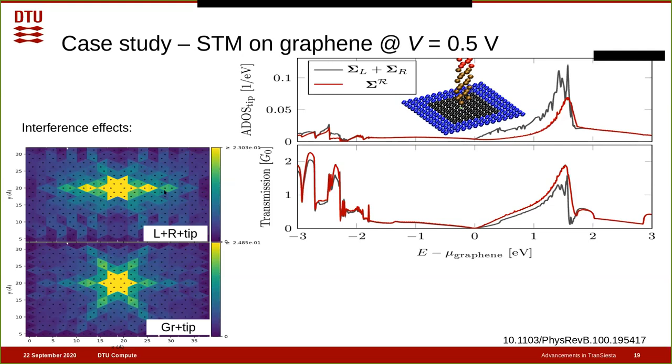Another thing is that when you plot the bond currents in this case, you can really see the effect of the interference effects. So here you have a left-right, so you have 3 electrodes, and here you have the real space self-energy. Here the neighboring tip is up on the north side of the plot, and that kills off the actual path that you will see in a correct calculation. If you do a really big tight binding calculation, what you'll see is a 6-star shape of the injected current from the tip. That's the true result, and that you will find by using a real space self-energy.